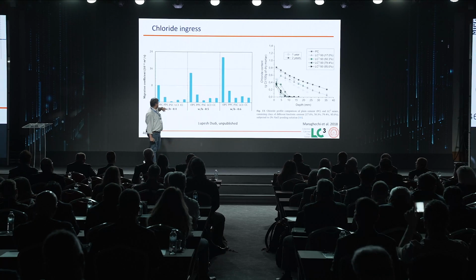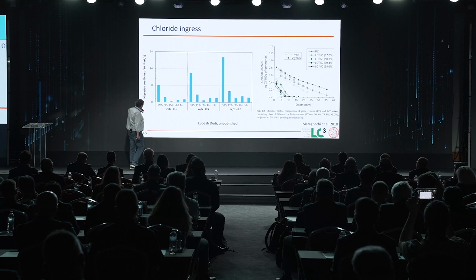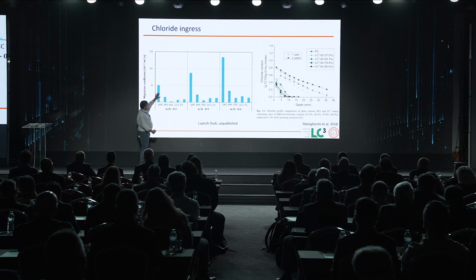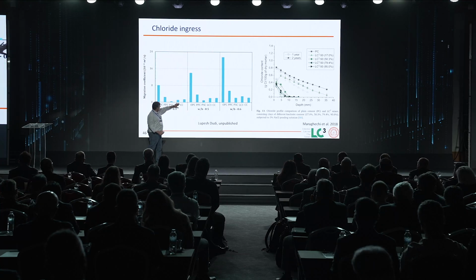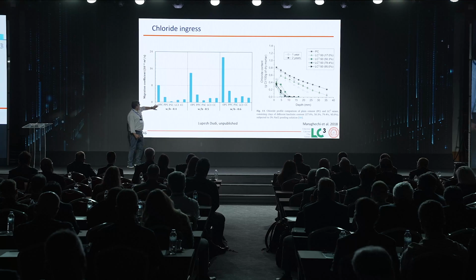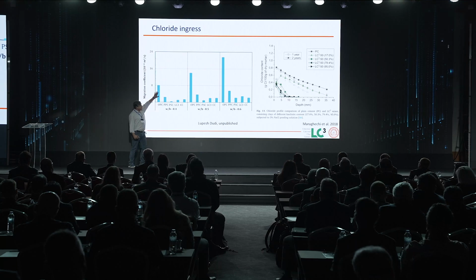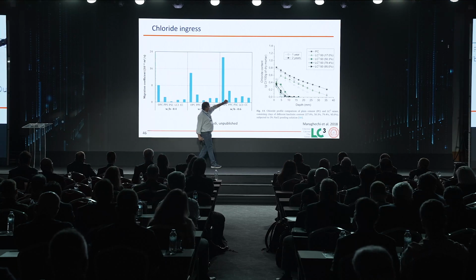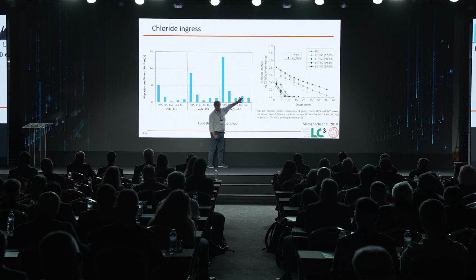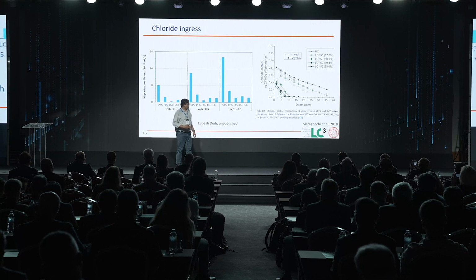And you see those chloride ingress values over there. You see over here the chloride ingress value in the case of OPC, in the case of LC3. You see the chloride ingress in the case of OPC at 0.4 water binder ratio versus the chloride ingress in LC3 at 0.6 water binder ratio. So durability-wise, this is way better.